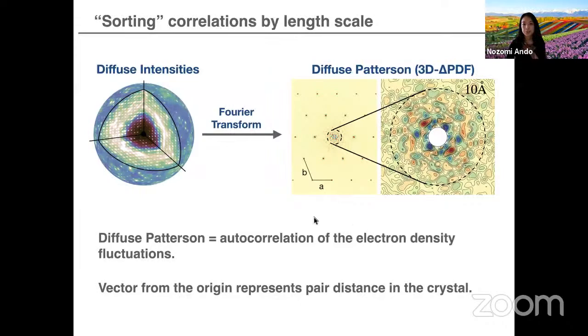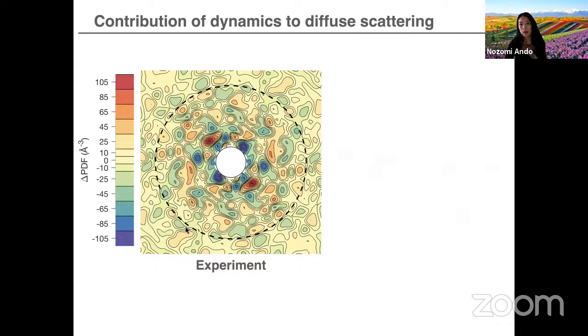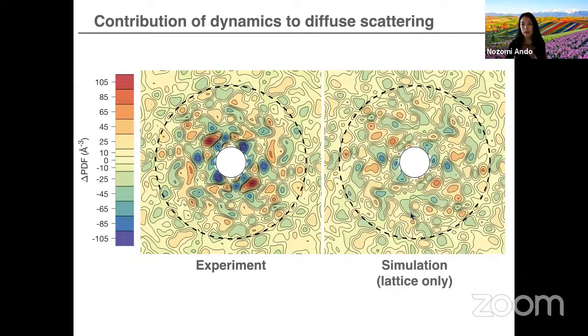So here I'm showing the experimental diffuse Patterson. And this is the simulated diffuse Patterson from the lattice dynamics alone. You can see that the shapes of these correlations are very similar, but the amplitudes are very different near the origin. In the lattice dynamics model, the proteins are treated as rigid bodies and they move. They're correlated over many unit cells. And so we can get correlations that are both short and long range, but not enough of the short range correlations.